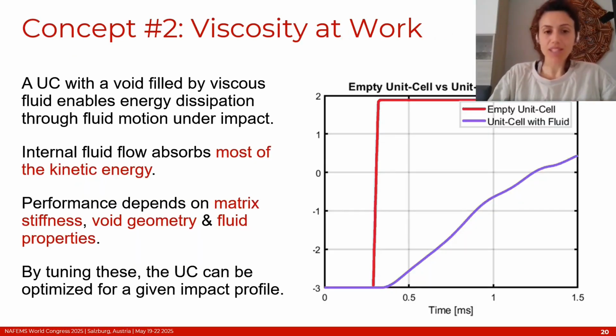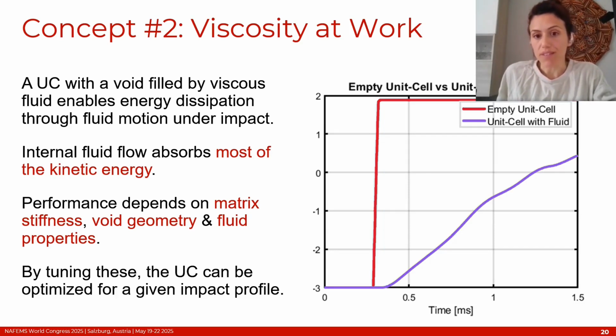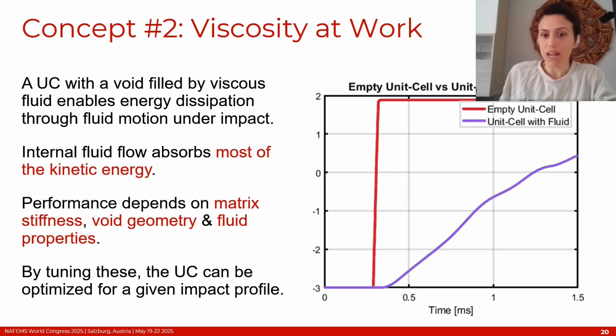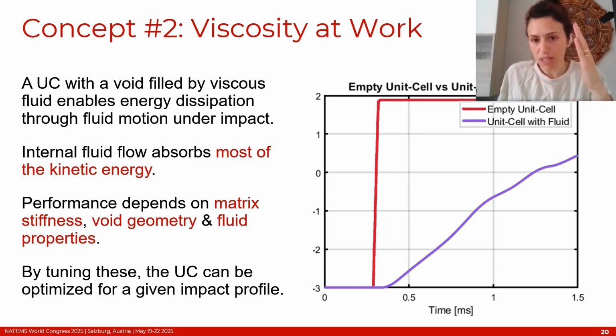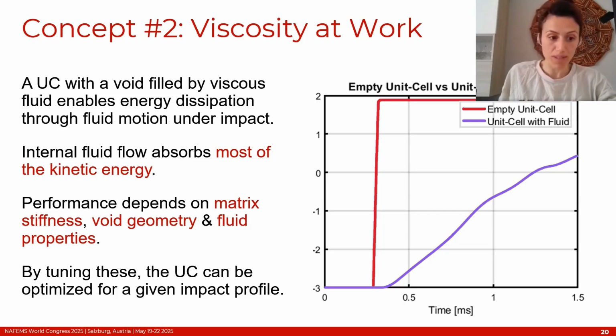The second concept is a unit cell with a void filled by viscous fluid, which enables energy dissipation through fluid motion under impact. Indeed, the internal fluid flow absorbs most of the kinetic energy. If you look at the velocity as a function of time on this graph, again, the red would be an empty unit cell, and the purple is our unit cell filled with fluid. The acceleration, which is the slope of the curve, is incomparably less abrupt. By tuning the matrix stiffness, the void shape, and the fluid properties, again, we can optimize the impact performance.